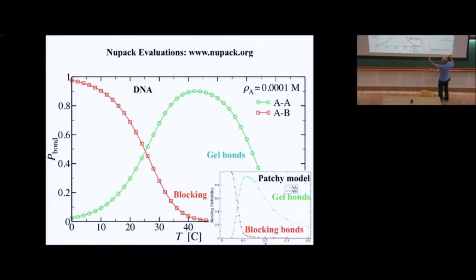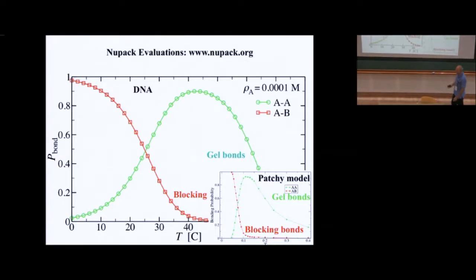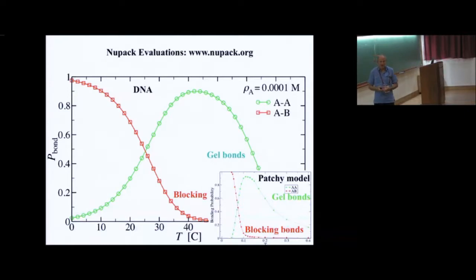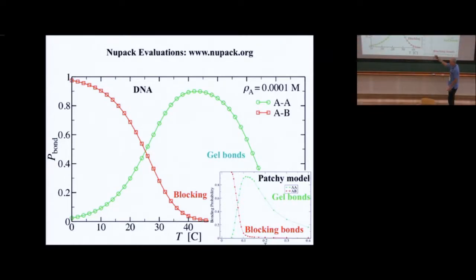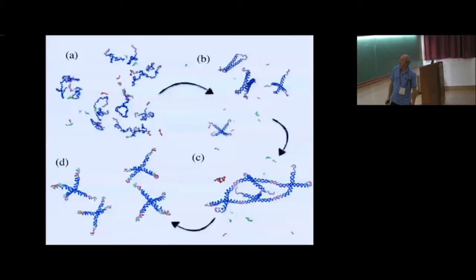Look at the temperature scale. Here, to see this process, you have to go a factor of 4 in temperature. And here you go nothing, right? 20, 30 degrees over 170, 300. This comes from the fact that this DNA binding is really temperature dependent. It's delta G that controls it. So you can really condense in a short temperature interval what would be impossible to do in an experiment on this time scale. For the temperature of your experiment, it's almost impossible. Okay. So good that we use DNA.